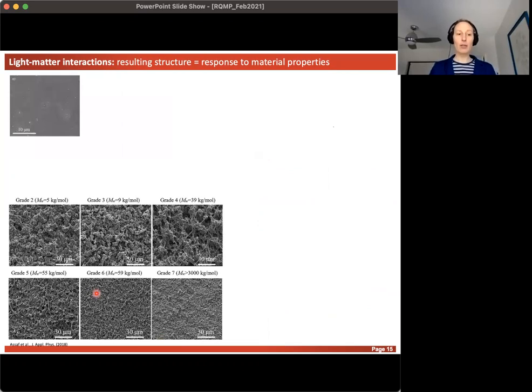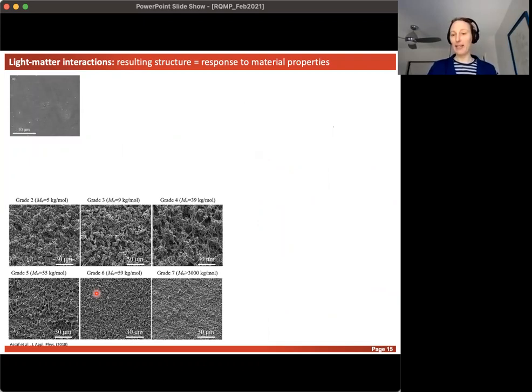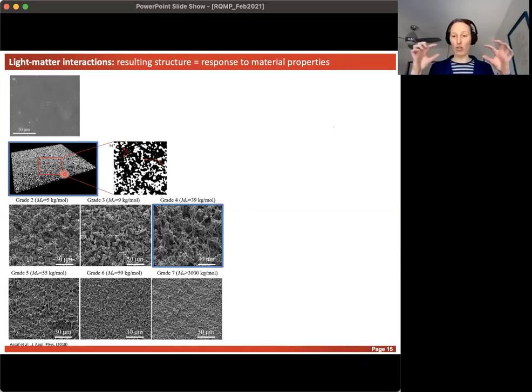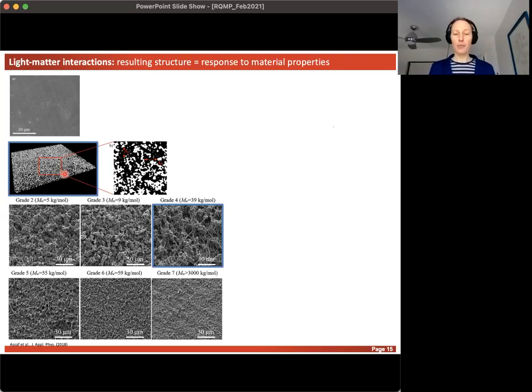We can still inscribe into a polymer, but in the laser-processed trench we will see that porosity. Here I show a shark-skin imitation as an example. For polyethylene experiments specifically, the material comes in many different grades with varying molecular weights while keeping chemistry constant. With increasing molecular weight but the same laser fluence, we get smaller pores. Taking grade four as an example — under CT scanning, those pores are interconnected throughout the machined layer with a porosity of 55–45%, which is interesting for filtration or cell scaffold applications.